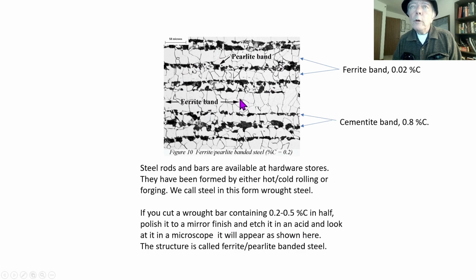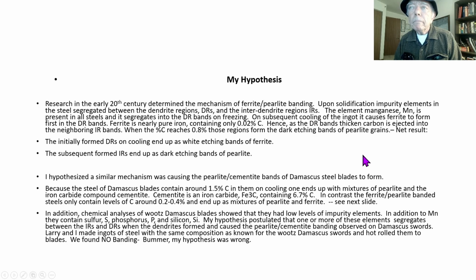You see these beautifully aligned bands of ferrite. See all these little grains? Those guys are all little grains of ferrite. And these black guys, they're all grains of pearlite. So these are the pearlite bands. So the pearlite bands consist of cementite grains, 0.8%, ferrite, or almost pure iron grains, little grains, 0.02 carbon. So knowing all that, I came up with the hypothesis.